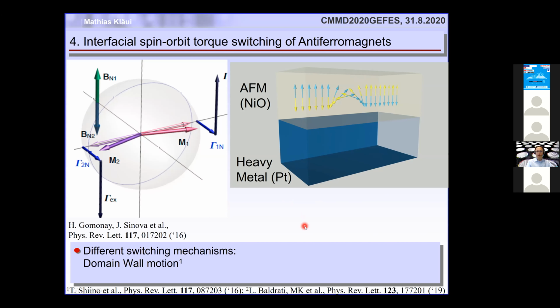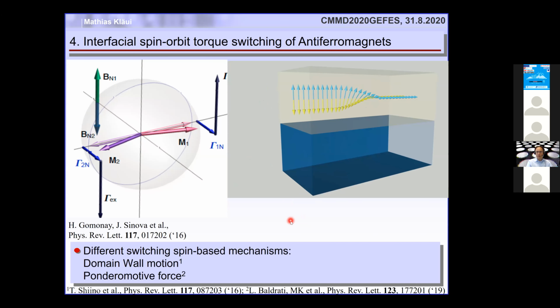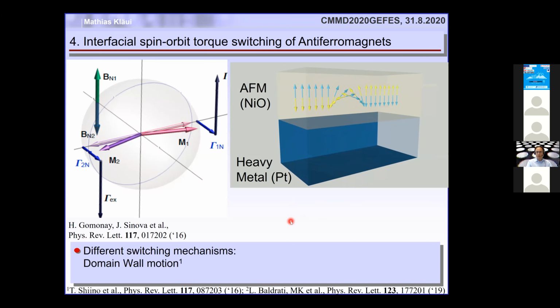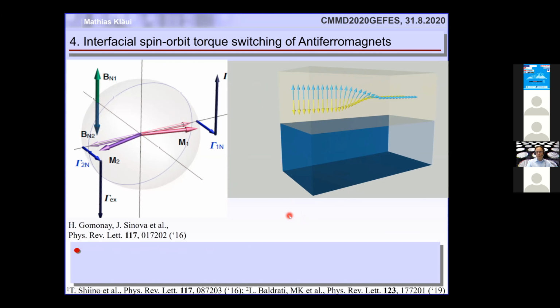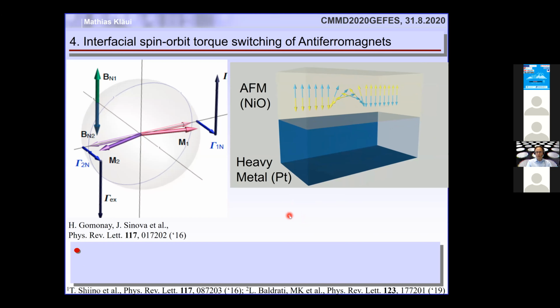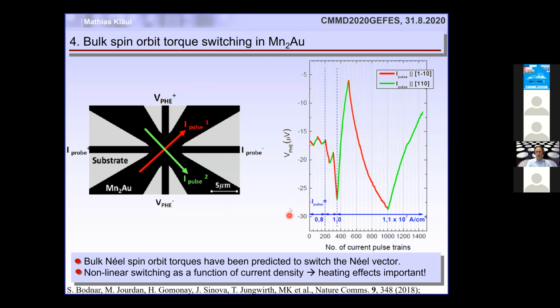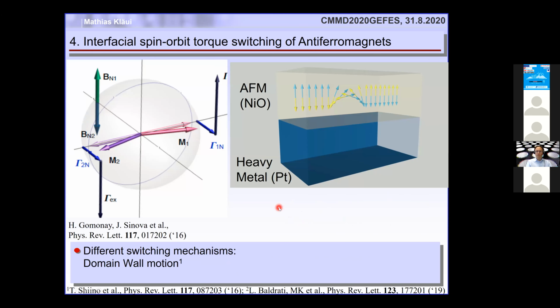And then it was predicted actually in, sorry, let me just go back to see the animation again. So it was predicted that indeed by having a spin orbit torque, you can actually move domain walls in this nickel oxide. So this is predicted here and in these two papers.